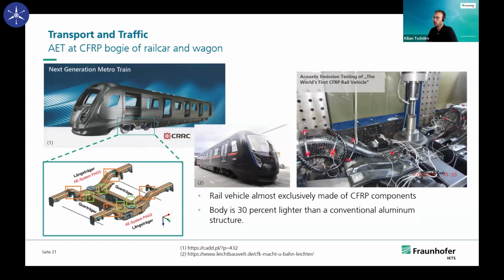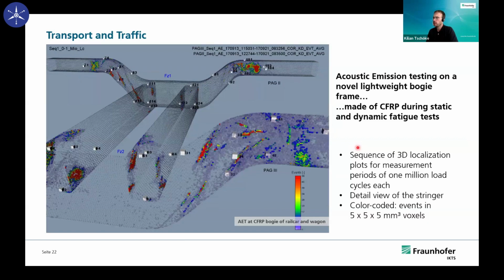You can see here these red dots. These are the acoustical sensors attached or clamped to the structure. And you can see the bending test. During these fatigue tests, we've done acoustical emission. So this means we've listened to the structure. And what you can get is, in the easiest case, a plot of localized acoustical events. Here you can see the geometry from the CAD model, and the colorful dots are the number of acoustical events coming from these positions.